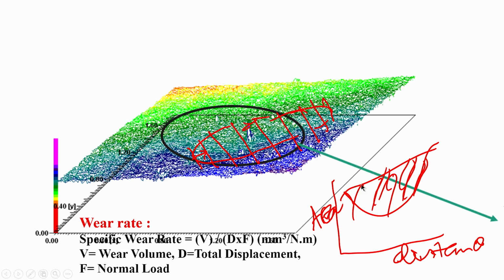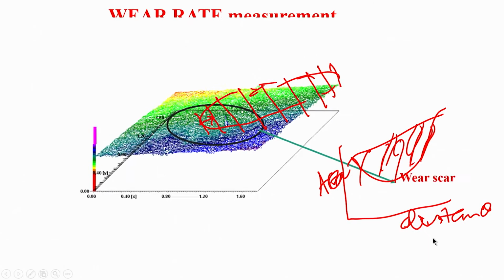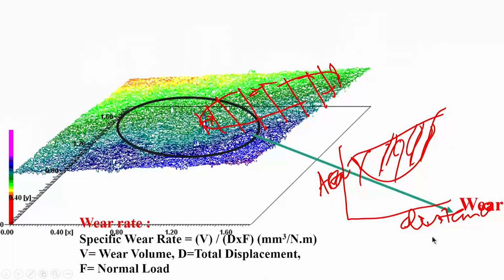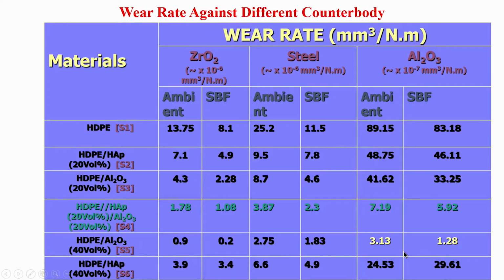So this wear volume you can use in calculating the specific wear rate. The specific wear rate is nothing but V divided by D times F, where V is the wear volume, D is the total fretted displacement, and F is the normal load. So then you get millimeter cube per Newton meter.